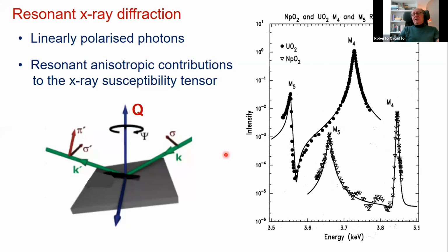And then in the presence of long-range order, the intensities of superlattice peaks are measured at resonant energy as a function of the polarization channel, mainly using linearly polarized photons with polarization parallel or perpendicular to the diffraction plane, and by measuring the modulation of the superlattice peaks as a function of the azimuthal angle, that is, while rotating the sample about the scattering vector, the Bragg peak vector.